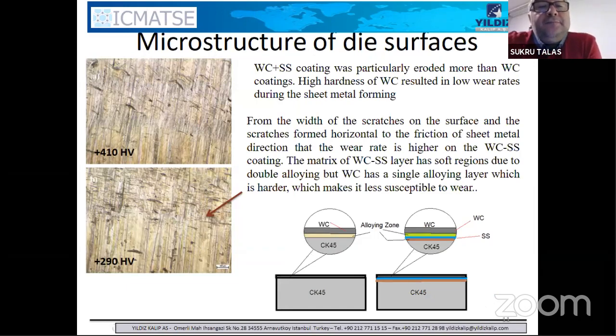So we did some optical work on the surface. As you can see, this one is tungsten carbide coated. This one is tungsten carbide plus stainless steel coated surface. So the base hardness was around 189 to 200 HV. The tungsten carbide plus stainless steel coating created 290 HV extra, so you can add it up to 490 HV. This one became 610 HV. So the hardness increased quite a lot.